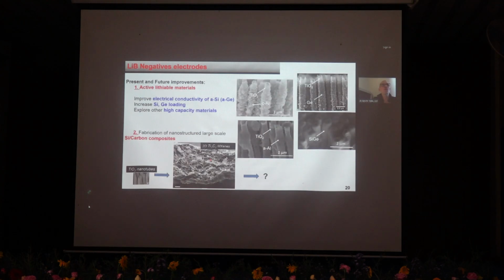So we worked on different materials, still using TiO2, to see how to improve the silicon we make by electrodeposition. One way is, for instance, to create an alloy with the silicon, because silicon is not very conductive, which is a drawback for negative electrodes, because the lithium has to be reduced inside the silicon. So we try to alloy silicon and germanium, but also silicon and aluminum. So we see here depositing aluminum, for instance, on TiO2. Here we can grow germanium, silicon germanium, so we try different kinds of materials.